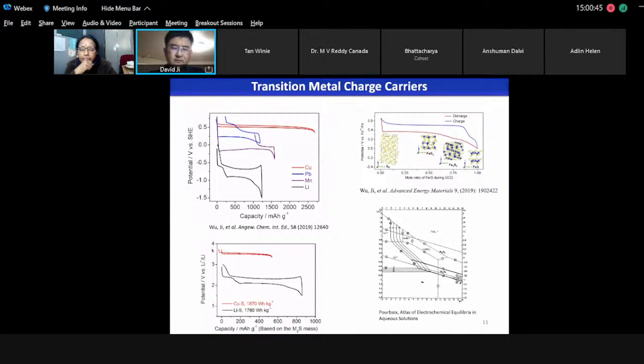For lithium, you do. The reason for this is the semiconductor nature of the cuprous sulfide and the cupric sulfide. It's not just about electronic conductivity. Cuprous sulfide or cupric sulfide, they're also ionic conductors. So they're both ionic and electronic conductors. That's why the polarization is extremely small. For lithium sulfide, it's not a conductor for any conductivity, right? We know it is insulating for ions and electrons.